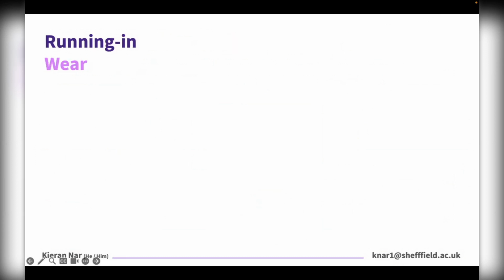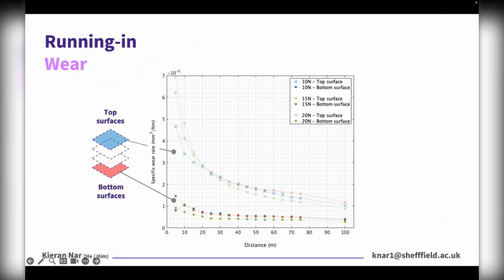And what we discovered might seem quite obvious now, but top surfaces, which we previously identified as being asperity peak dominated, experience greater magnitudes of wear than bottom surfaces, which we found to be relatively Gaussian during initial sliding. So because these top surfaces were asperity peak dominated, they incurred greater amounts of asperity peak fracture and wear in general during running, as represented by the steeper curves in this figure.